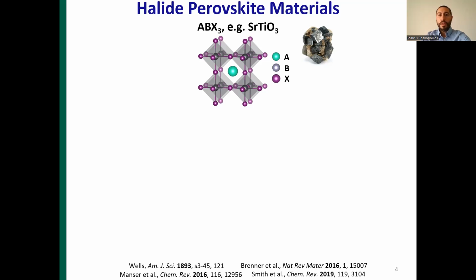The general formula is ABX3, where A and B are cations of suitable size and X are anions, again of suitable size. I mention sizes because in order to acquire the cubic aristotype structure of strontium titanate, there are some size limitations that must be fulfilled. The structure consists of BX6 octahedra that span the three directions, whereas in the formed cuboctahedral cavities, A-site cations reside, charge balancing the structure.